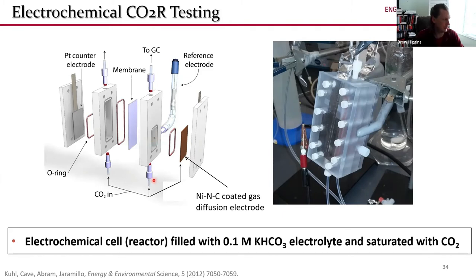During these measurements, as the CO2 bubbled in and flowed out of our cell, we sent that to a gas chromatograph so that we could do product detection and quantification on the gas phase products that were produced. And then at the end of these experiments, we stopped the experiment, opened the cell up, and collected the electrolyte to do NMR on, to see if there were any liquid products present in there.